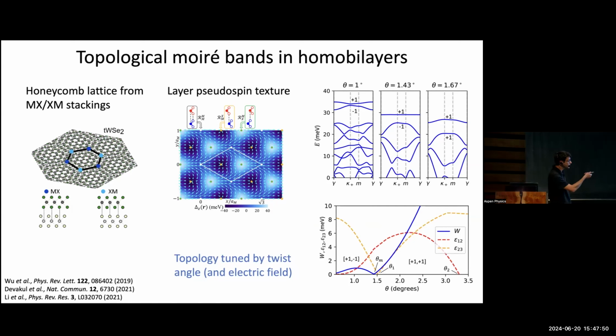And in fact, depending on what your specific twist angle is, it's been theoretically predicted that you get different topology out. And that can be controlled both by twist angle and by the applied electric field, which changes the relative energetics of these two different blocks.